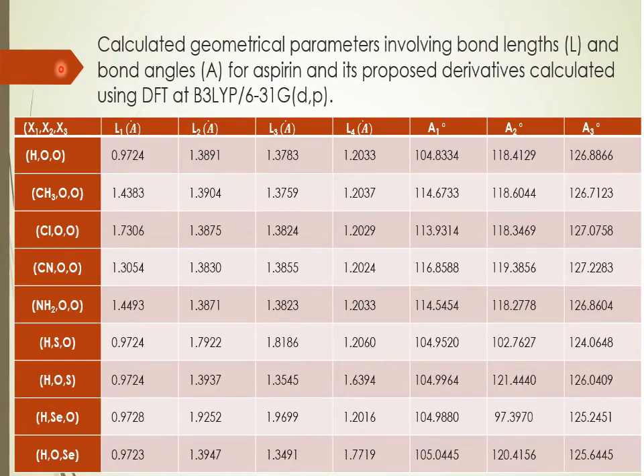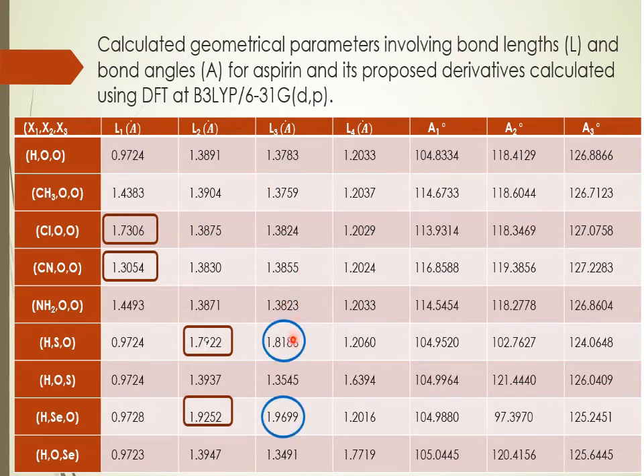This table shows the calculated geometrical parameters involving bond lengths and bond angles. Here we can conclude that chloride has the highest value and cyanide has the lowest value compared to the groups substituted at the X1 position. And in this column, we can conclude that sulfur and selenium have the highest value compared to the whole column. For L3, sulfur and selenium in position X2 also have higher values compared to their position in X3.